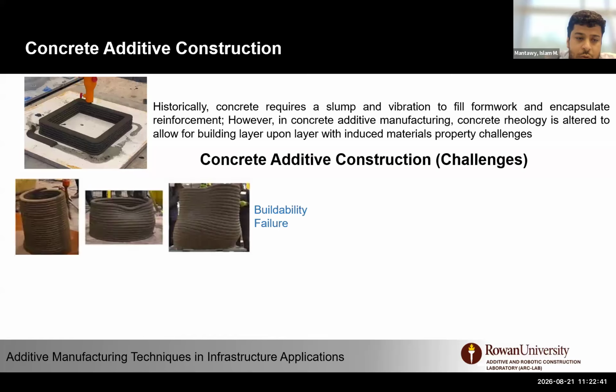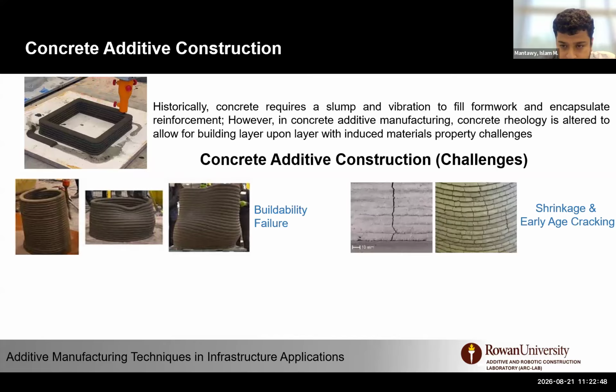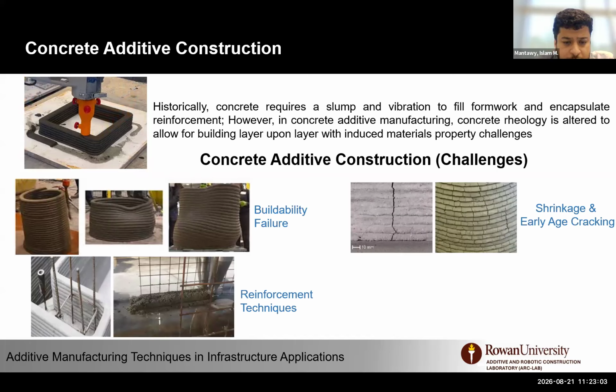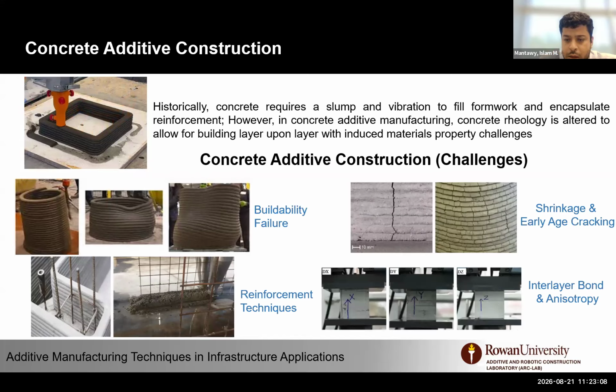Those challenges include buildability failures during the print because of not tuning the material rheology, or early age shrinkage and cracking, because instead of having the cast concrete encapsulated in formwork, now the entire structure is exposed to the environment and elements. One big challenge is reinforcement techniques, or how to integrate reinforcement. And for sure, as with any 3D printing technique, you will have anisotropic behavior and interlayer bond problems.